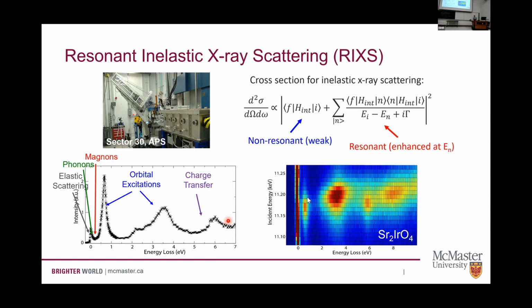You mentioned that some of these materials you only grow really small crystals. Why is that? Is that a limitation of the material? Yeah, it seems that they're difficult to grow. Mostly we grow them with flux growth, which tends to produce smaller crystals anyway. The iridium is really expensive. So even if you could find a system that would grow well enough that you could try a floating zone growth, it would probably cost you about $10,000 worth of iridium. So it just seems difficult to crystallize a lot of these materials and to grow them at size.